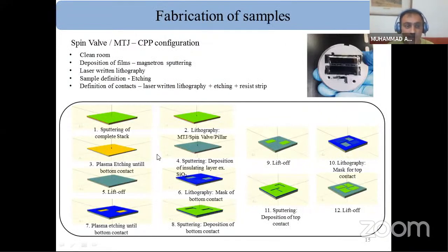For fabrication of complex samples, we also make current perpendicular to the plane devices. You have to use successively magnetron sputtering, lithography, and etching equipment. This process takes 13 steps for fabrication of one sample. But due to some reason, we could not use the plasma etcher. Therefore, for CPP samples, I have used a physical copper mask, which I prepared using lithographic techniques.